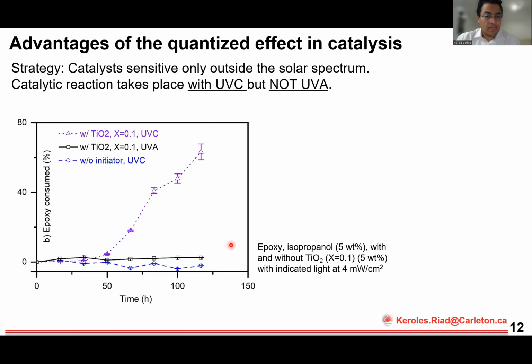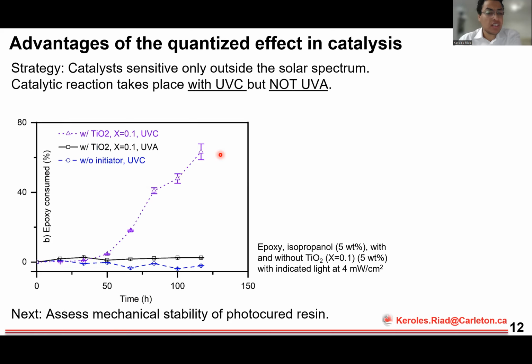And this is exactly what you see here, where with titanium quantum dots under UVA light, you don't see any reaction, the same way as in the previous graph. Without any initiator under UVC light, you don't see any reaction. But with UVC light, you have the typical photocuring reaction again. So this is essentially achieving the goal and premise of the research, where you want the quantum dots to control what kind of light actually triggers the catalytic reaction. Next for me is to assess the mechanical stability of the photocured resin, which usually is the ultimate goal here.